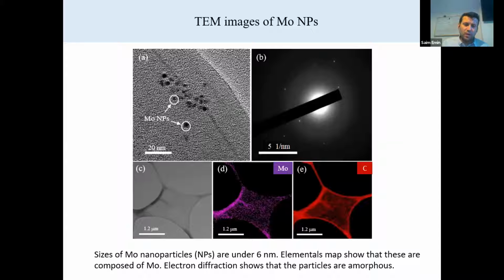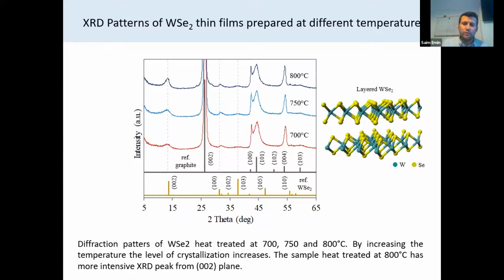Here are images of molybdenum nanoparticles, which we also used to grow molybdenum diselenide. As you can see, they are very small. They are amorphous. We don't have many spots. The electron diffraction is quite blurry. There are a few spots, but compared to the number of particles, this is very little. So the majority of these particles are amorphous.